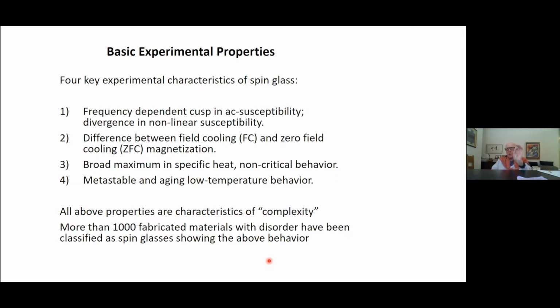We can tune all the behavior of the spin glass with a magnetic field, with its orientation, with its frequency, with its pulsing. So then we go on to the specific heat. There is non-critical behavior in the specific heat. However, at low temperatures, there is this unusual metastable state with remanences, with irreversibilities, and in particular with aging. If I let the system sit for 10 to the 4th or 10 to the 5 seconds, that's a week of time, I find that the system is constantly evolving. I need fine measurements to detect that, but it's constantly evolving.